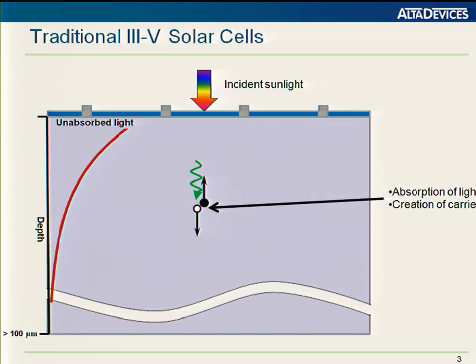Traditionally in this community, III-V cells are grown on thick gallium arsenide or germanium wafers, and there's no particular attention paid to the absolute thickness except as far as yield and wafer breakage and things like this. There's no particular attention paid to the reflectivity of this contact. So even if the device itself is thin, only a few microns, the overall structure is very thick. And because the refractive index is basically matched throughout, the optical structure is very thick.